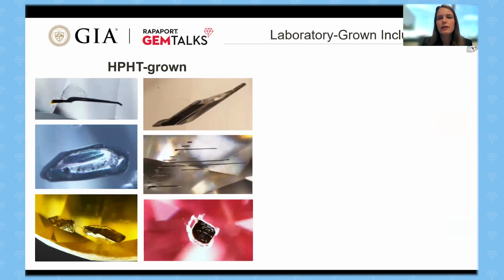Now, if we move to the laboratory-grown diamonds, the HPHT-grown diamonds, in particular the older products, were really susceptible to trapping some of the metal flux that they were grown in. So little chunks of metal that are trapped within. Oftentimes, these inclusions have rod shapes, and they can have this metallic luster to them.